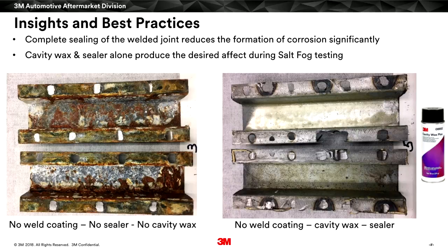So we sealed that joint together from the outside. We didn't weld through the sealer. And then we used cavity wax on the inside. And you can see that weld flange is just pristine. And this is after 500 hours in the same environment that the rail on the left was exposed to. So going back to what Chrysler and Honda were saying about no weld-through, well, you can see that as long as you seal that seam and you use cavity wax, you don't need weld-through. You're good to go.